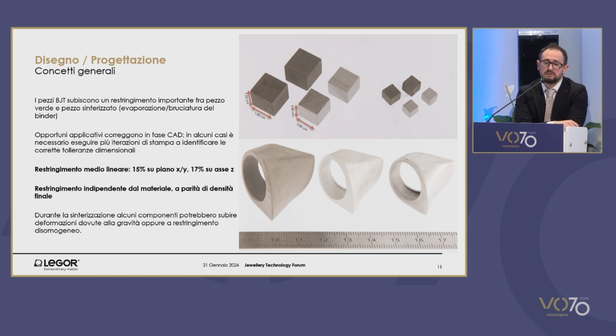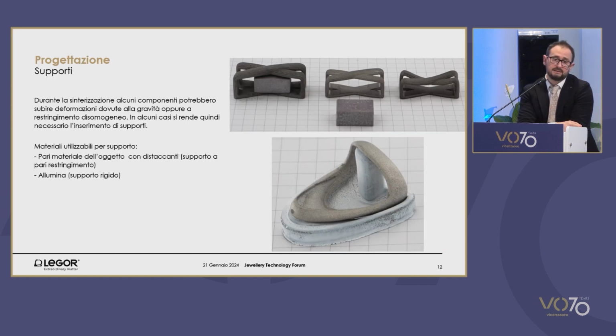This means that if the item has not been adequately placed in the sintering oven, it could be distorted by gravity, or the shrinkage in areas close to parts that have a bigger mass could actually be strained in an irregular way, leading to undesired distortion. To tackle this problem, during the design phase, it is possible to produce supports. You can see on the left the green and two sintered objects in steel, which during printing have been printed just as they were, without that brick that you can see here, which is made of alumina.